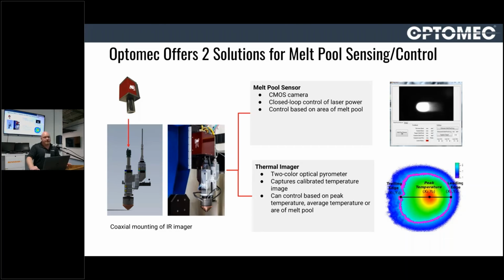The other one is a thermal imager. What this thermal imager does is it actually looks at the true temperature of the melt pool. That's very key because you can plot it over time and see that you're maintaining the same temperature, which basically is maintaining the same cooling rate, which goes to your material properties that we were just talking about. The key with this thermal imager is it's a 2-color pyrometer. If you have a single color pyrometer, you basically have to calibrate every material that you're going to run on that system. You'd have to plot a temperature curve. With the 2-color pyrometer, you're looking at the difference between the low pass and the high pass. That means regardless of the emissivity of the material, I still get a temperature reading based off of the low and high pass differential.